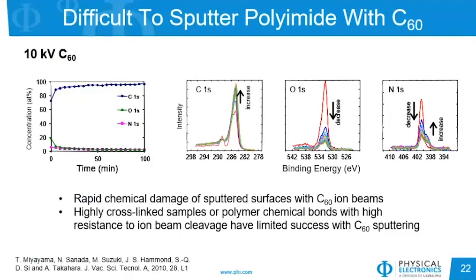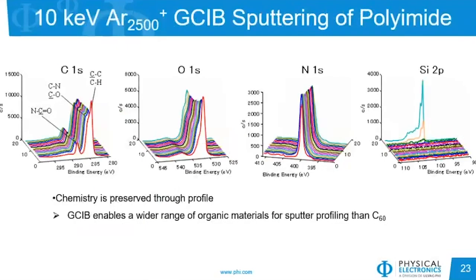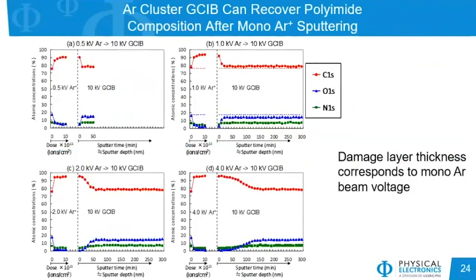This was one of the ideas that prompted us to develop an additional ion source beyond the C60, which led to the development of the gas cluster ion beam with argon. As you can see here, with a 10 kV argon 2500 sputtering of polyimide, we can sputter through the material and maintain the chemistry. And as I've shown previously on PET, we can also use the gas cluster GCIB to recover from a damaged layer as shown on polyimide when we have sputtered with monoatomic argon.